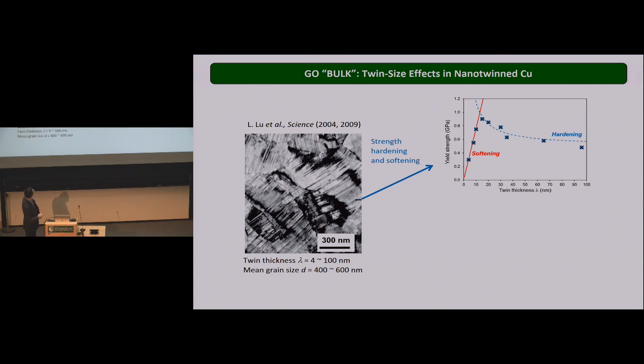This is the first work that has been published already more than 10 years ago about the first nanotwin copper film in Science. And here what people have described in the literature for almost a decade, these interfaces are perfectly coherent. And so they produce much higher mechanical strength than the typical metals. In particular, when you decrease the twin size, that is the spacing between two twin boundaries, we find a large hardening behavior. But to a certain limit, beyond that, the material becomes softer. And that was strange at the time.